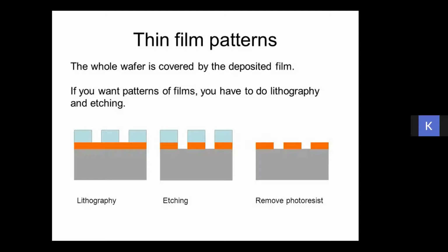So first is the lithography, you do the patterning, then you do the etching part. Either you do the etching part or you do the metallization part and then remove the photoresist. So it can also happen that you don't do a lift off. What you can do, you just first deposit a metal or any other thin film material on a silicon wafer. So first you have the thin film, then you do all the processing of photolithography and then make a window, and then you do the etching.